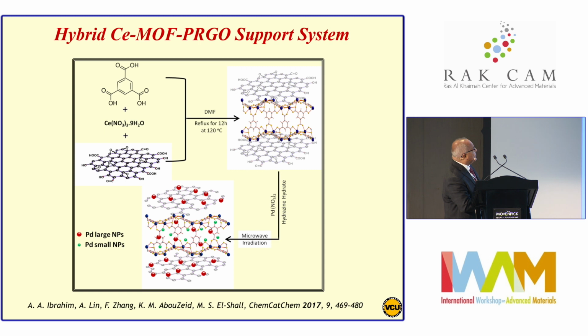The approach that we used to increase the activity of this MOF support is to incorporate a layer of reduced graphene oxide in a hybrid structure. So the idea here is to synthesize the cerium-MOF at the same time in the presence of graphene oxide during the DMF reflux process. And we're hoping to achieve construction of the MOF layered below and above the reduced graphene oxide, because of course the next step will be the addition of the palladium catalyst through palladium nitrate.